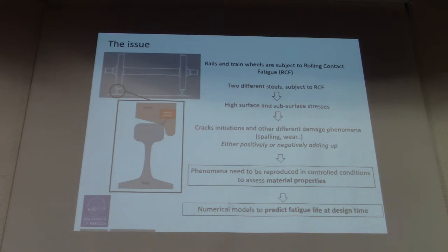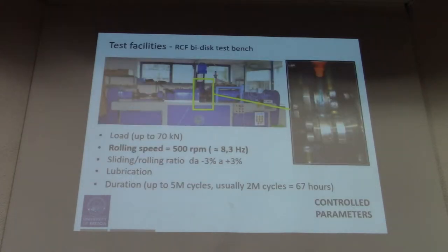To do so, in our lab we have some test facilities. In particular, we have our rolling contact fatigue test bench which can control parameters such as the load, the rotary speed at 500 rpm, the slide-rolling ratio, the lubrication, and the duration of the test.